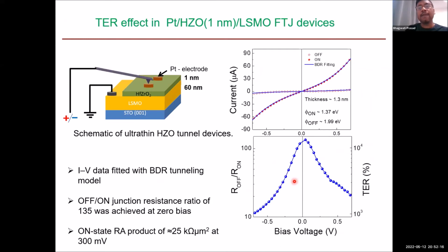So then the aim is to make the ferroelectric tunnel junction. We deposit the platinum, and then we pattern the platinum top electrode. So here you have LSMO as a bottom electrode, this is the ferroelectric insulator barrier layer, and this is the top electrode. Then you switch them one way or the other. We first apply plus minus 3 volts, and then we switch them, and then we measure the IV for the 2 states, for one polarization state and the other polarization state.